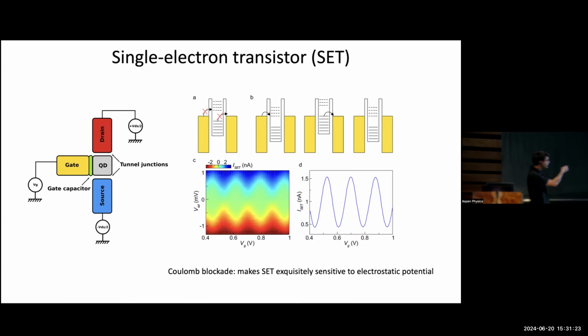On the other hand, if you have some gate nearby that can electrostatically tune the energies of states within this metal island, you shift these states up and down, and you can come to a regime where it's possible for an electron to hop from the source to the island, then from the island onto the drain. And in this condition, you get conduction. So this together gives rise to a pattern known as Coulomb blockade. That is, current from source to drain has some periodic modulation as you tune the electrostatic environment of your island. And this is ultimately what we'll be using. Basically, this response is what we'll be using to measure the sample.